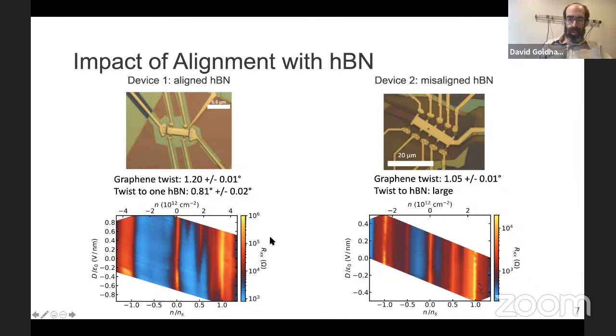And then if you look more closely, you'll see that the scale of resistance that I showed is actually much higher in this case. And so I find that color maps like this can make things really jump out that you wouldn't notice otherwise, but I also like to say that they can hide a multitude of sins. And so it's really useful to look at line cuts through them to get a more quantitative sense of what's going on. So let's take cuts in these two cases at fixed displacement field, but varying density, and see how they look.